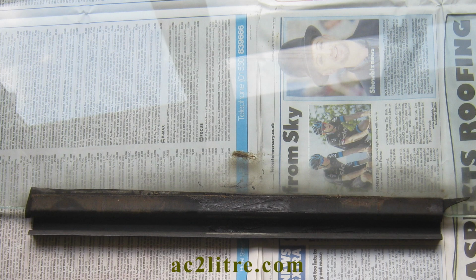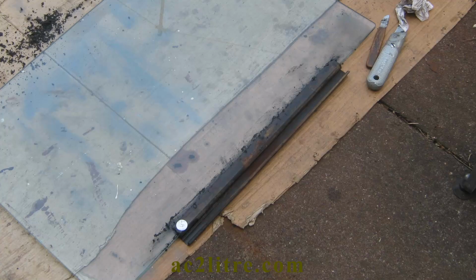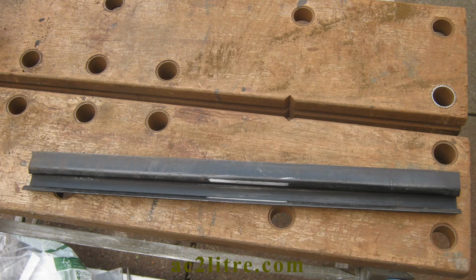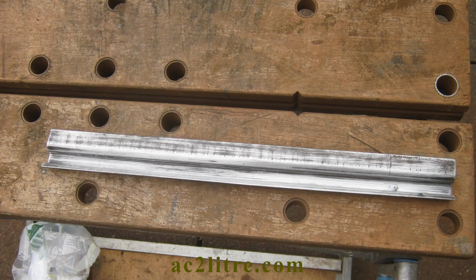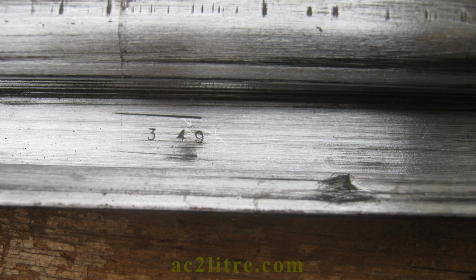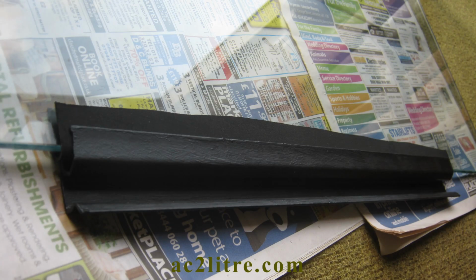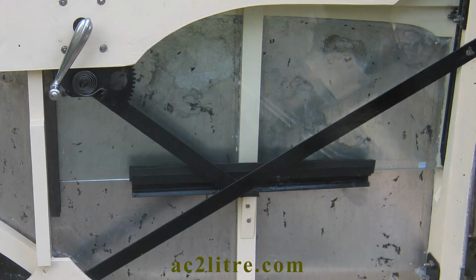The one difficulty was removing the glass from the groove or runner that holds the bottom edge. There is a thin rubber seal and it had effectively glued the glass to the steel. I added solvent cleaner to dissolve the ancient rubber and cut away the rubber with the craft knife. Even the steel runner was date stamped. I pressed the window back in after making a new rubber seal. It tended to pop out again, but eventually got the message and stayed put. And very nice it looked once finished.